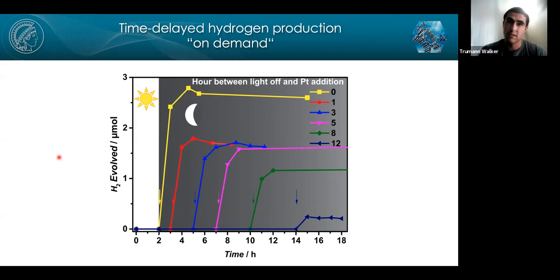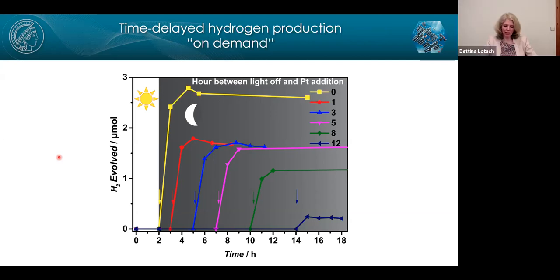So you don't have any measurements where you constricted the amount of oxygen entering the system and observed whether the charge loss was either greater or less? Well, no, of course. These were done by trying to really exclude oxygen. We just, apparently, didn't do a good enough job in doing this, but it's not in air or something like that. We try to exclude oxygen, but I guess that is your question, we haven't done really any systematic study on finding out what exactly the loss channel is here. It might be a conglomerate of things, and we really need to look at this in more detail, but it hasn't happened so far.